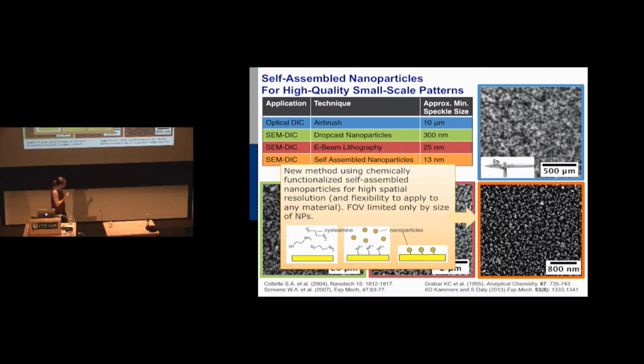So we figured this chemistry out, and at the time we were buying nanoparticles from Ted Pella for like $100 a little vial. Again, not feasible. So we actually now make our own nanoparticles. There was a procedure published by Frens in about 1972. You can build your own nanoparticles for about $2 a bucket, which is great.